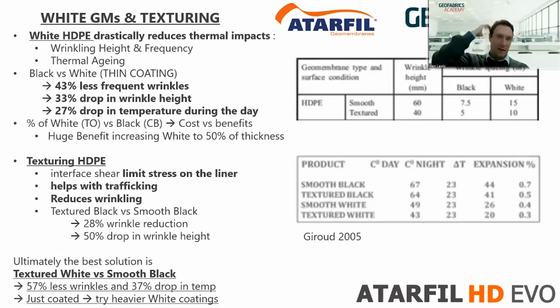And so I'll just touch on white geomembranes and texturing, because they do have some benefits aside from just aesthetics and slope interaction. White HDPE has been found, this is nothing new really, and this is some pretty old data actually pulled out, but it does reduce wrinkling height and frequency when you use white membranes. So that's good for easier installation. It keeps it cool if it's a hot environment, so you can install maybe during the day rather than at night. It reduces the temperature, so it slows that thermal aging process.